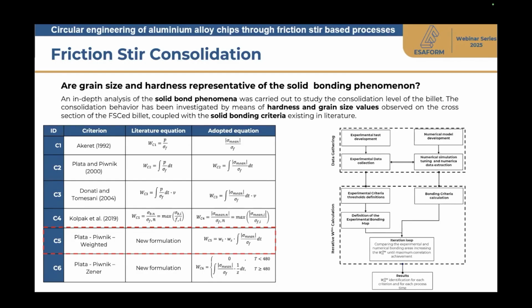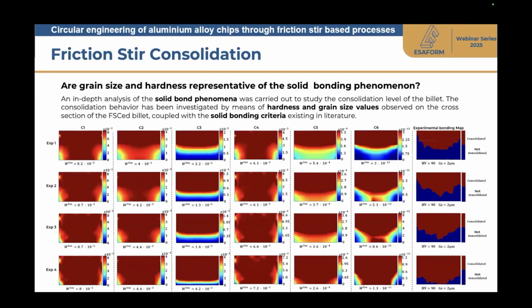Of course, the criteria were tested starting from a collection of experimental data and also a collection of numerical simulations. In particular, from the test we derived from the experiments, we derived the local values of Vickers hardness and also the local values of the grain size. And in turn, from the numerical model, we got the information useful in order to carry out the integral calculation of the proposed criteria. Well, in this way, we had this kind of maps.